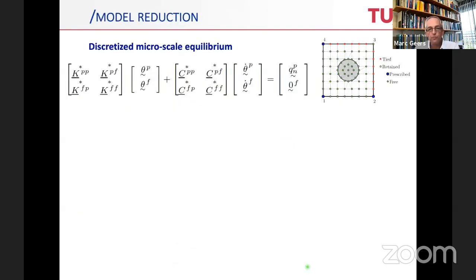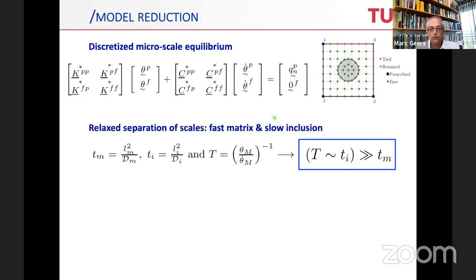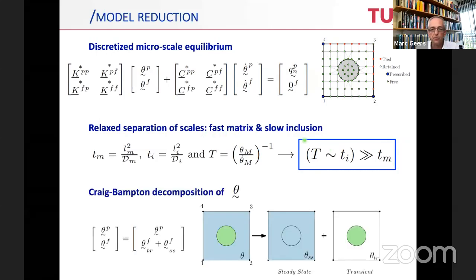If we solve that problem, you would typically set up a discretized microscale equilibrium equation. We look at the problem in a particular scale separation regime, which is similar to the previous case, a relaxed separation of scales. It's the regime in which the time scales of the loading can be comparable to that of the inclusion, but are much larger than that of the matrix. So typically a fast matrix and a slow inclusion, to say it simply.